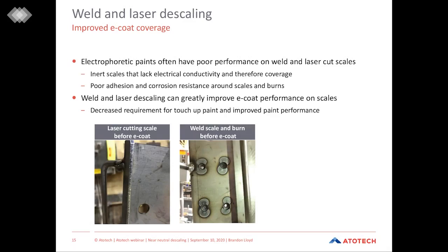So you can see in the images on the bottom, we see another laser cut scale part. This is before e-coat. And the image on the right is the weld scale and burn area before e-coating as well. So these areas would present issues if they were not addressed prior to pretreatment and the e-coat application.